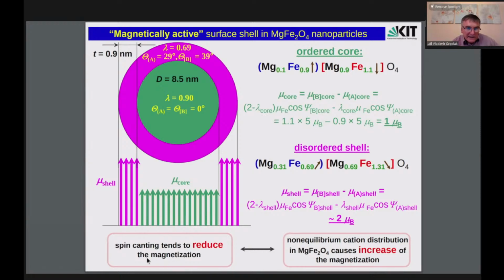I mean, we see that the enhancement which we observed using SQUID or magnetization measurements is attributed to the effect of cation distribution, which causes increase of the magnetization, and spin canting tends to reduce it, and these 2 effects are always competitive, and in this case non-equilibrium cation distribution won.